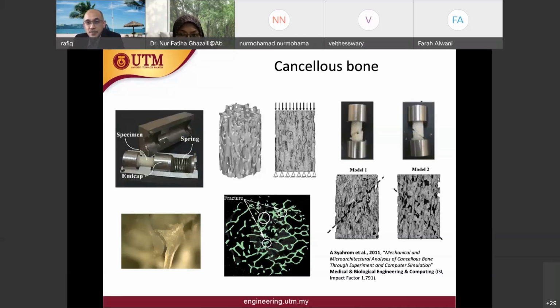Again, extremely difficult, and it involves hundreds of thousands of elements to construct. Then we compress it using MSC Marc, a finite element software, and look at the fractured segments. And for that particular bone, we test using Instron equipment, compressing it until it fractures, and you can see clearly this 45-degree fracture site for both bone segments.